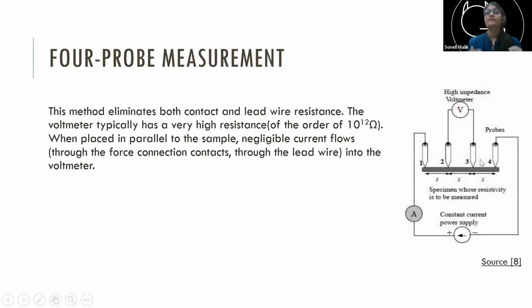So a better way of finding resistance, especially in samples that have very low resistance of themselves. Say if my sample resistance is 1 ohm and my contact resistance is 100 ohms, then the two-probe method will be absolutely useless. So in that case, people have come up with a four-probe measurement. Now, what a four-probe measurement does is you have one set of probes connecting to the ammeter, which will measure the current across your sample, and you have a constant power supply here. The second set of probes is placed inside of these current probes, the sense probes. So these connect to a voltmeter, which is in parallel to your sample.